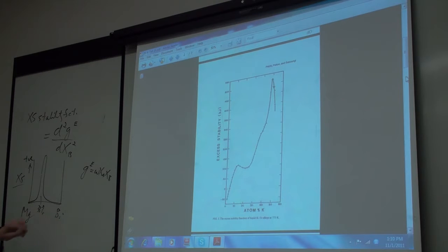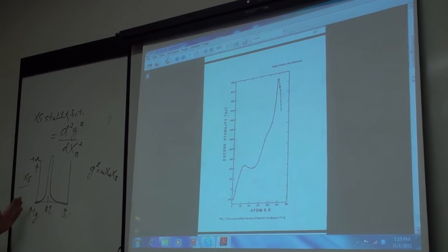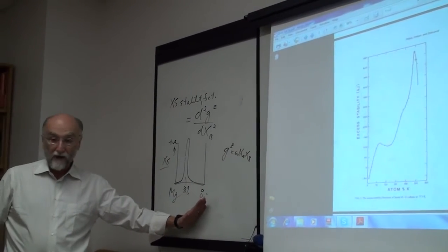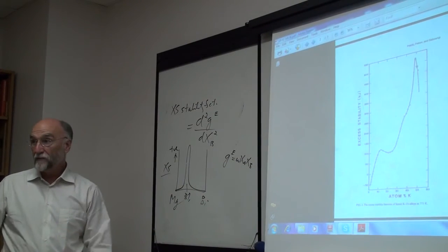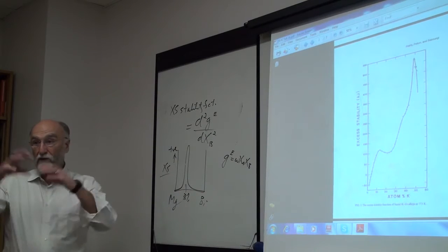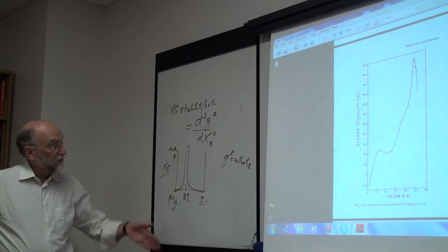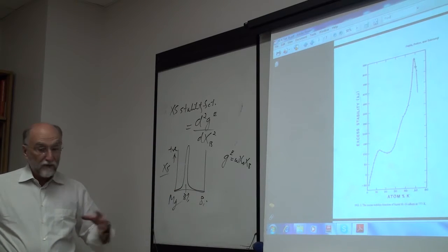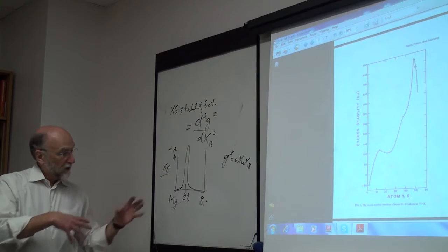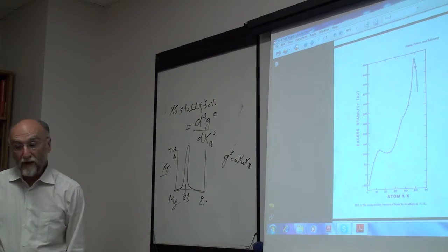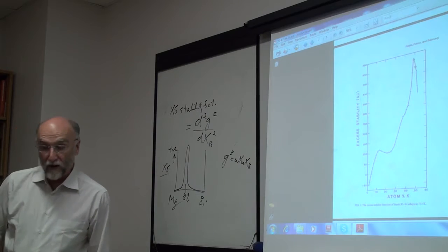I mean, magnesium and bismuth are like this. If you have two materials, this one is quite electropositive at the left of the periodic table, and this is electronegative at the right. That's when you expect to have short-range ordering. The positive ions tend to surround themselves by negative. It becomes kind of semi-ionic, if you like. It's still an alloy, but the magnesium has a tendency to lose charges to the bismuth, and so electropositive and electronegative elements tend to form strong bonds.